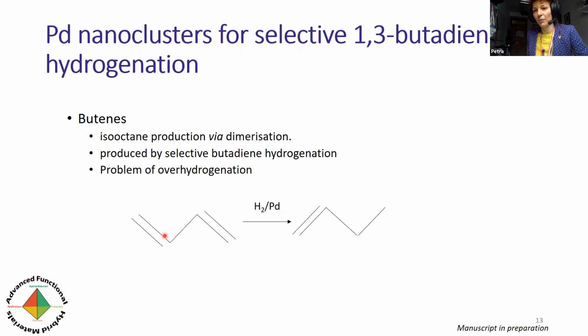So we have 2 double bonds, and we would ideally only like to hydrogenate one of those. Now, palladium is a known catalyst for this, and this is also an industrially relevant reaction. So this is a good model system for us. However, there is a problem of overhydrogenation in which we get from the butadiene to the butane rather than to the butene. And of course, this is something that we would like to avoid. Now also, and I just put it there in advance, it has previously been hypothesized that this might be a consequence of the presence of the hydride phase. So we were wondering if we can inhibit the formation of the hydride phase, we can also inhibit the overhydrogenation